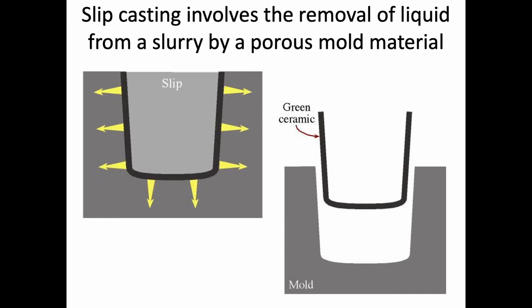But it's called slip casting because we have what's called a slip. This is a liquid that has our ceramic powder in it. So this is basically a slurry. And what we do is we take that liquid, that slurry, and put it in a porous mold. The reason we put it in this porous mold is that it will remove the liquid from the slurry, leaving behind only the ceramic powder. And it will form that green shape that we want.